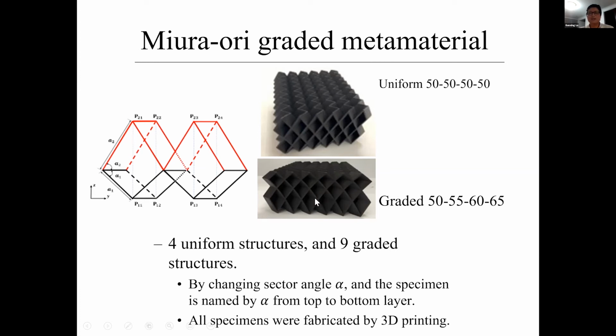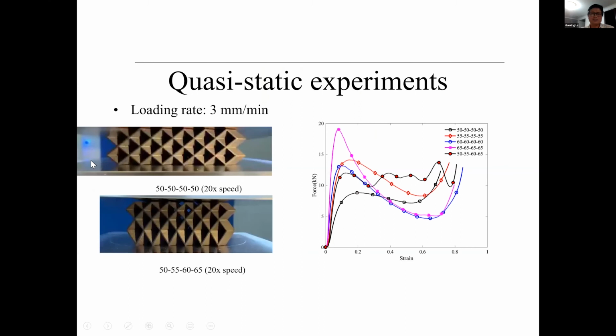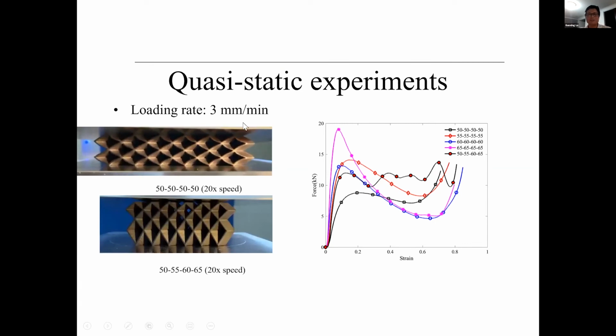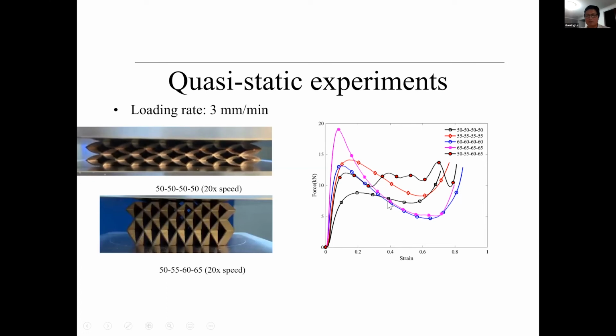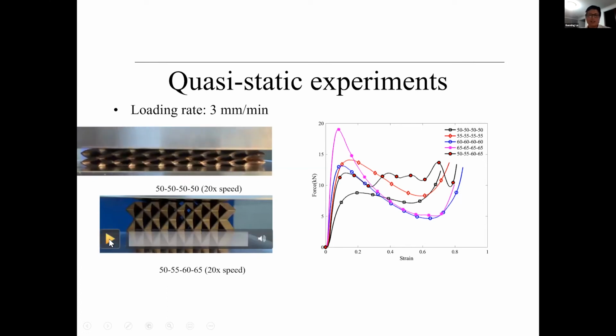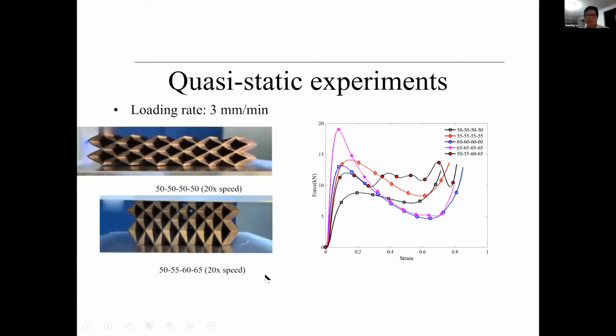And we tried this, we 3D printed this metamaterial, and then we even crushed it. So that is for the quasi-static case. This is made of a polymer, it's not made of metal. So we crush it, and on the right-hand side we get the force displacement curve. The top one was for the uniform, and the bottom one was for the graded material.